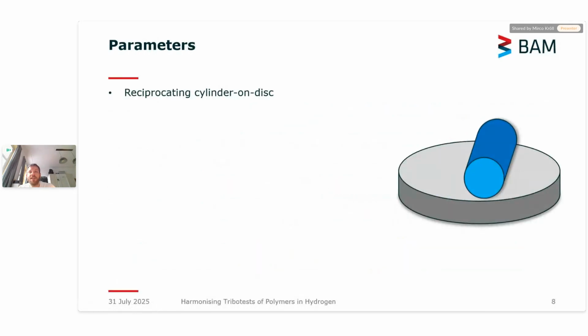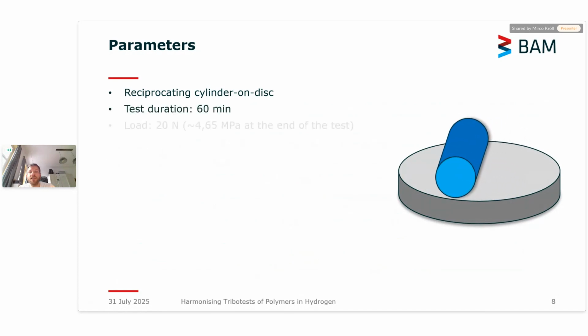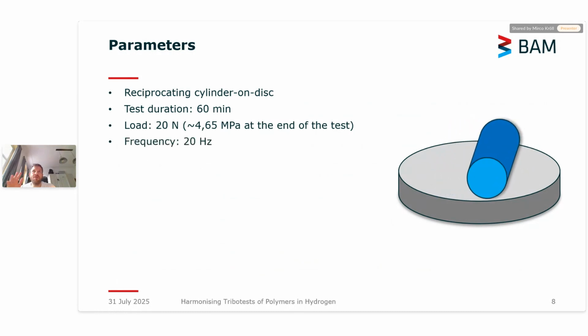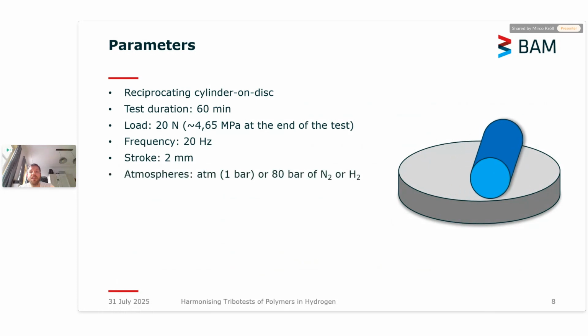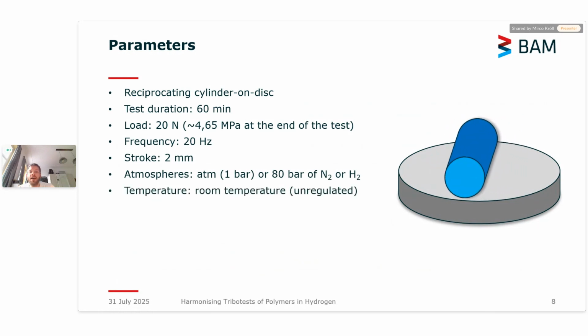The parameters of our tests: all tests were done in a reciprocating manner, cylinder and disc. We tested for 1 hour at 20 newtons, which ended up roughly at 5 megapascal, a typical contact pressure for sealings in hydrogen compressors and shaft sealings. We tested at 20 hertz with a stroke of 2 millimeters, at atmospheric pressure or 80 bars of nitrogen and hydrogen, depending on the tribometer. The temperature was room temperature. We didn't regulate that, so we didn't heat and we didn't cool.